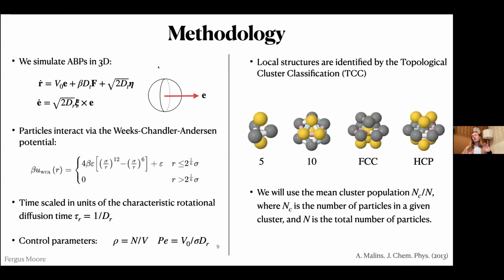So like I said, I'll be using active Brownian particles. They will interact through the Weeks-Chandler-Andersen potential. And the control parameters that are important to this work, we're going to use the total density, which is just the number of particles over the volume of the simulation box. And we'll be changing the Peclet number by keeping the rotational diffusion coefficient constant and changing the propulsion velocity.